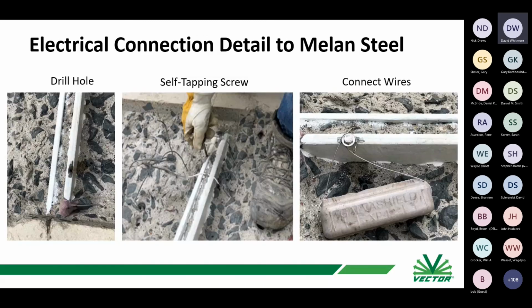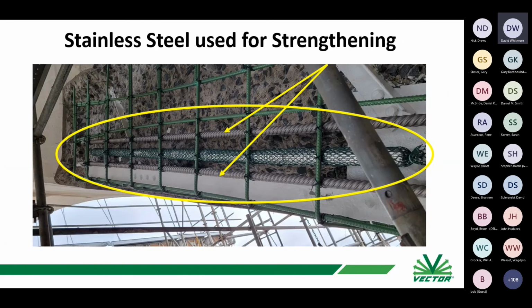Are there any concerns with that stainless, that close to the galvanic anode? A small amount of current is going to go from the galvanic anode to the stainless, assuming it's electrically connected with the other steel, which in the end it probably will be. It's not going to draw very much current from it though, because stainless steel is not a very good cathode. Because of the nickel in it, it doesn't actually take very much current compared to normal black steel. We go through great lengths to cover every galvanized piece of embed next to stainless steel in the bridge deck, right?